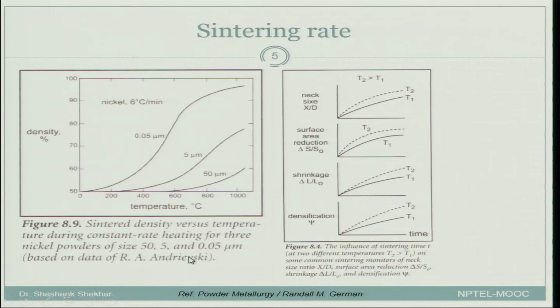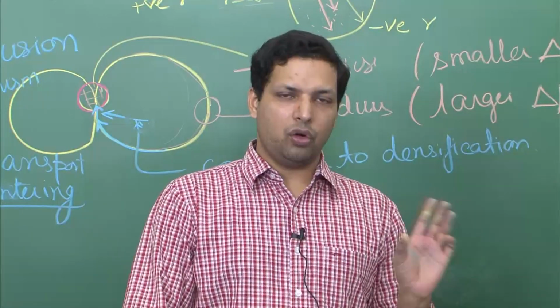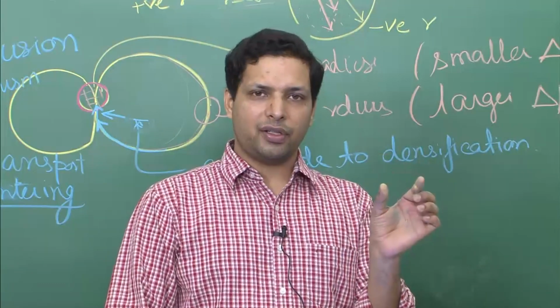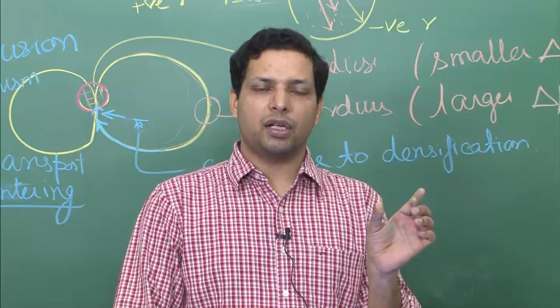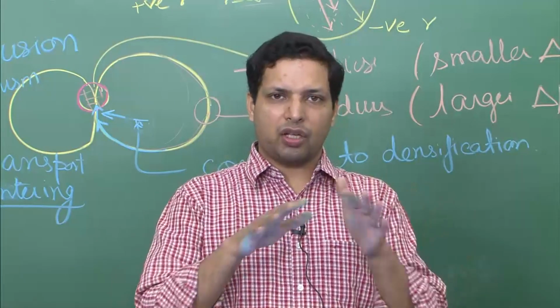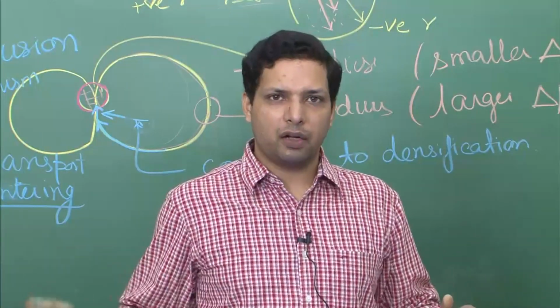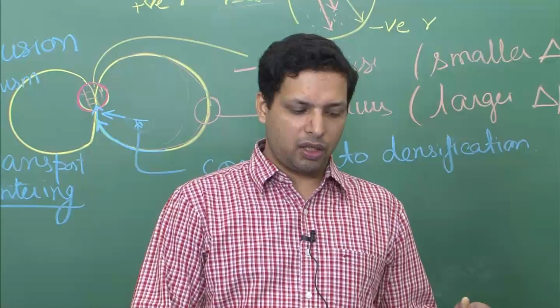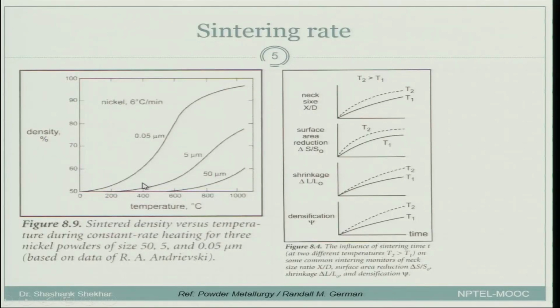Here is some more information about sintering rate. We said particle size will make a difference. We also said that what stage you are at will also make a difference to the sintering rate. So, here we see one plot that describes this. On the y axis you have density, and again whenever we talk about sintering rate, in the end we talk about density. So, densification is taking place at the macro scale. Only when we look at the definition of particle to particle distance do we differentiate that not all mechanisms of sintering will lead to densification. But when we look at the big picture, the whole compact, whenever you are doing sintering, there will be densification occurring, and that is why on the y axis you see percentage density, and on the x axis you have temperature.